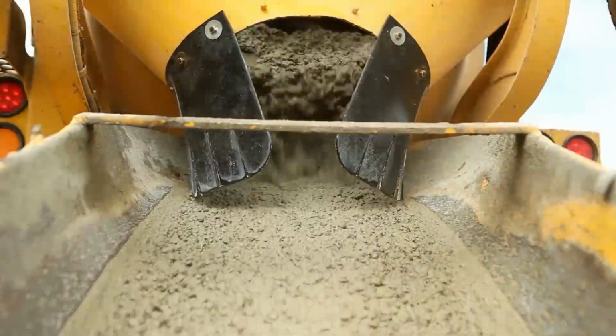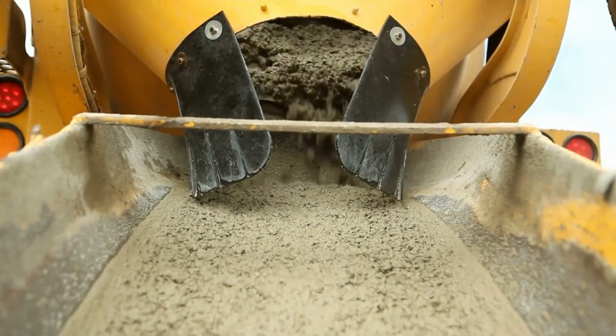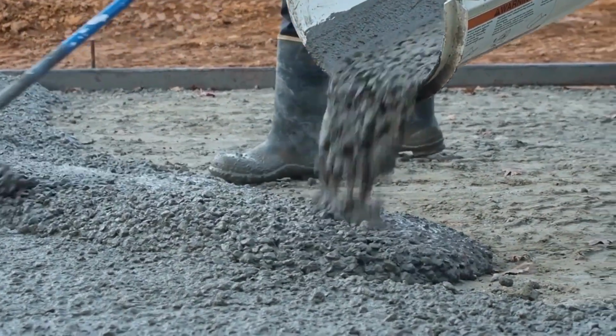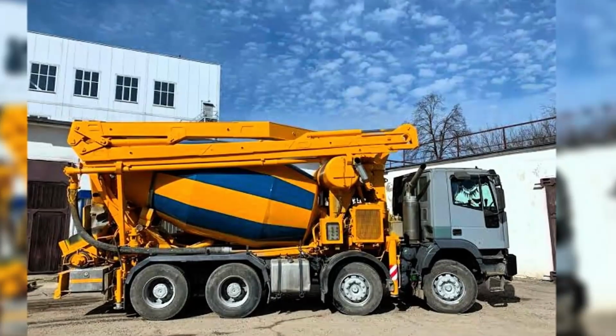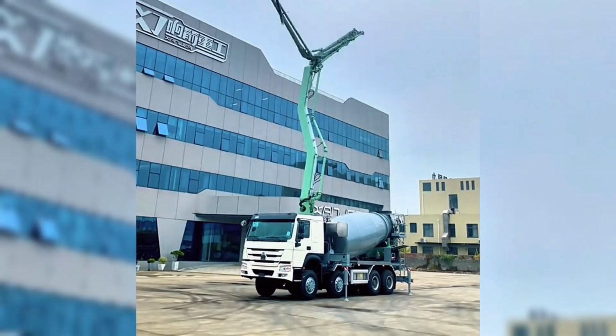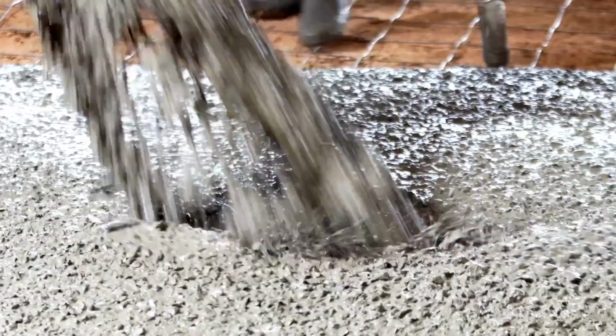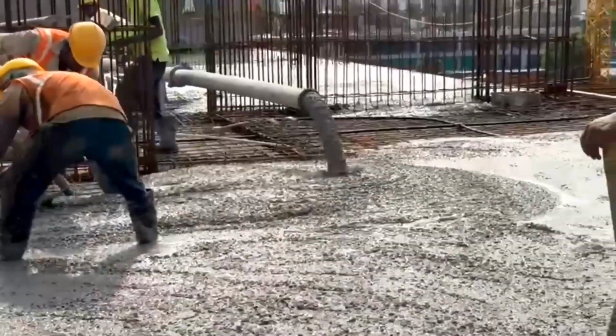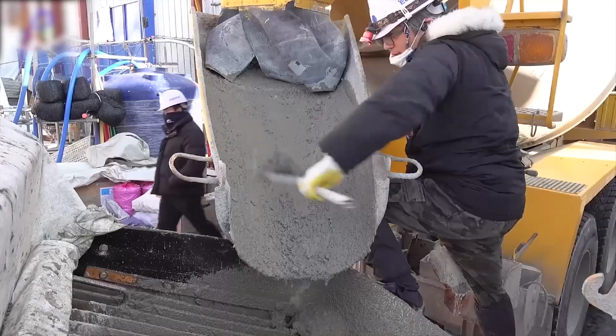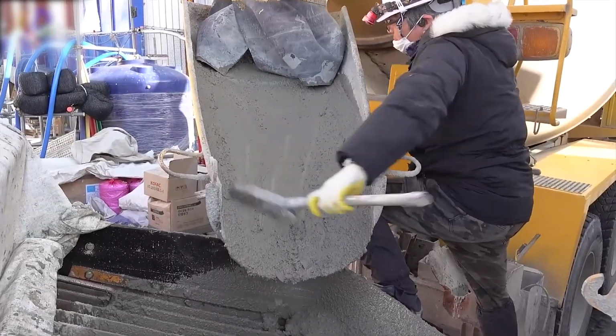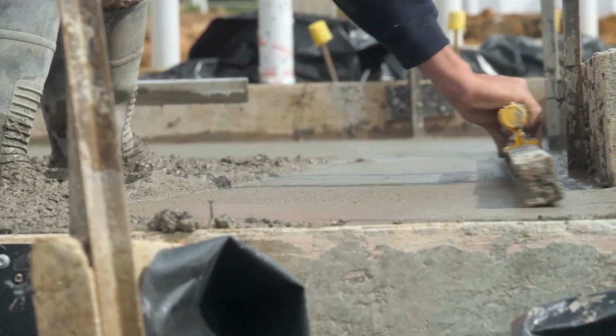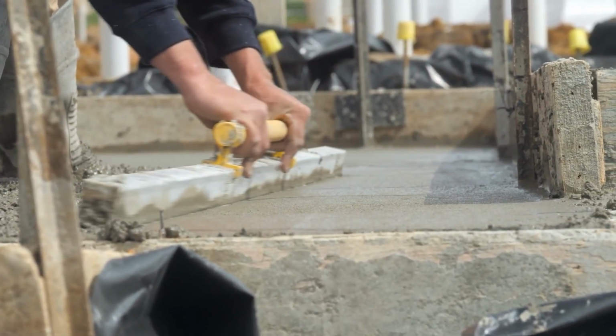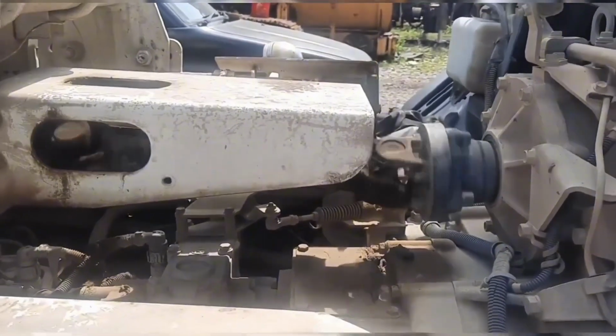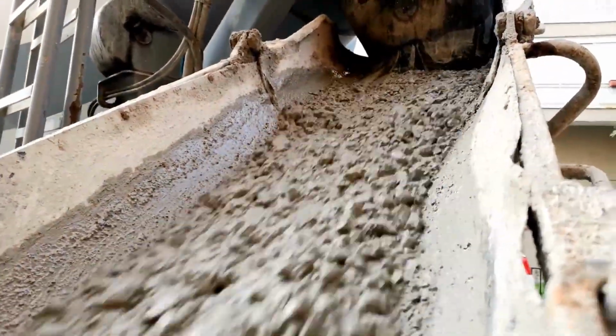A full truck of concrete returned is roughly 1,000 to 2,000 euros in direct losses before you factor in the truck's time and fuel. If the hydraulic drive fails while the truck is sitting in traffic and the drum stops completely, the hydration reaction does not stop with it. In hot weather, the mix can begin setting in under 20 minutes of no movement. Once hardened, the concrete bonds directly to the spiral blades. Removing it requires either a worker climbing inside with a jackhammer, ultra-high pressure water jetting at up to 40,000 psi, or in severe cases, cutting the drum open with a torch.